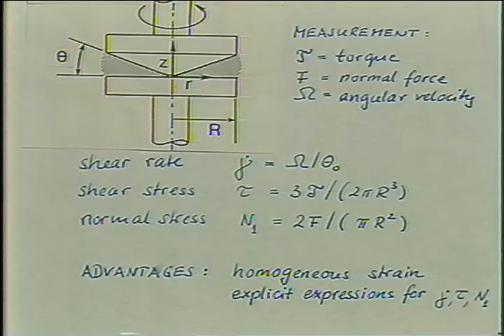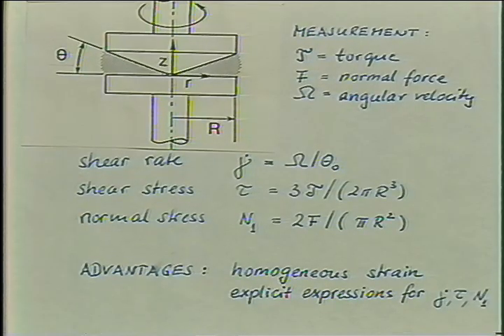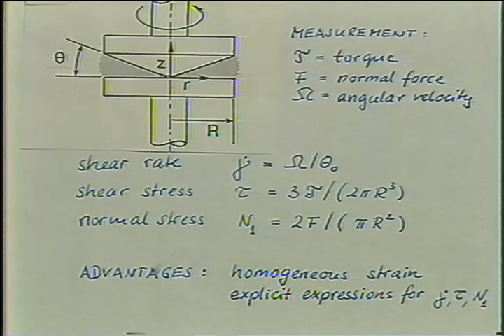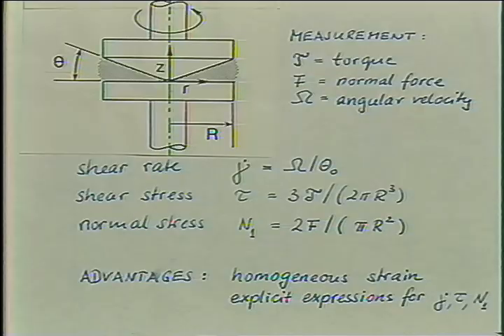At high rates, secondary flow will be induced, so the flow field is not the shear flow which we would like to have. Edge failure might occur, and there is the problem with the gap adjustment. If our sample changes density, we're kind of out of luck.